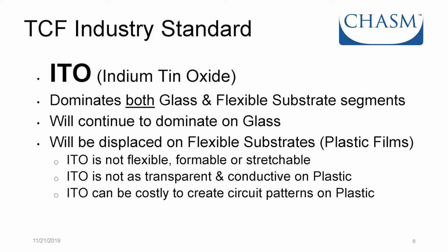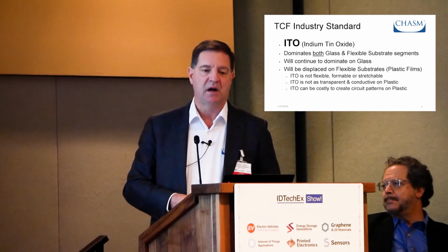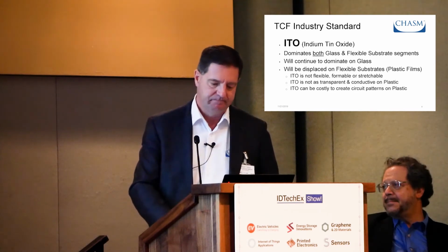ITO is not flexible, it's not formable, and it's definitely not stretchable. It also is not as good on plastic as it is on glass. The transparency and conductivity properties on plastic are inferior to on glass because of the temperature limitations of the plastic. And ITO, as well as the metal mesh and silver nanowire materials, can be costly to create circuit patterns on the plastic films.